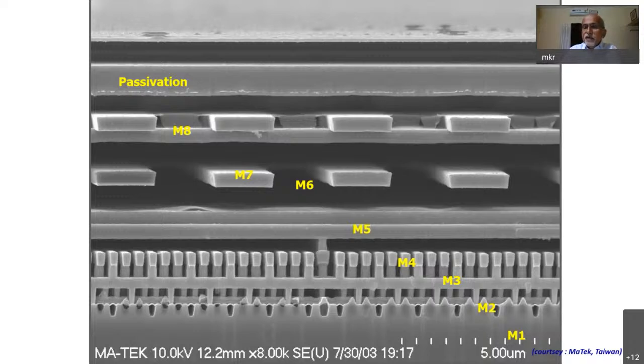This is from Matek, which is a Taiwan company. It's my partner company, where we do the physical analysis. We have made it specifically for students, and this device has only 8 levels of metal: M8, M7, 6, 5, 4, 3, 2, 1, and this is the passivation. And you see the metallizations. The gap you see here is the interlayer dielectric, which is already etched away.